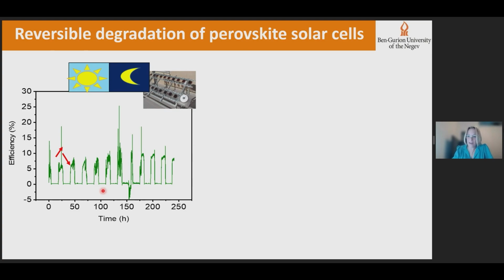To understand better the mechanisms that are correlated with that, we went on to doing some indoor light cycling experiments. And without going into the details, the biggest difference that we see between photovoltaic performance under light and during the dark cycles are in the short circuit current and the fill factor, which probably means that there is some reversible mechanism that is correlated with charge collection that we can detect when we look at light cycling, first outdoors and then indoors, but you couldn't really even detect it if you just use the conventional constant illumination tests that are typically used to study stability.